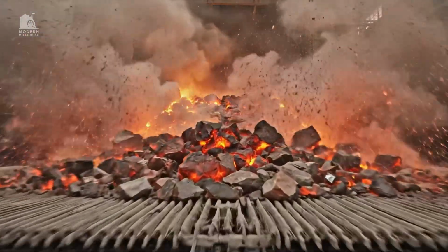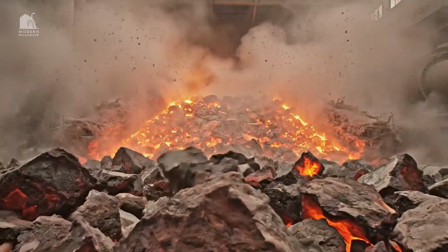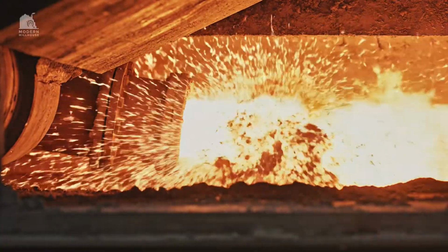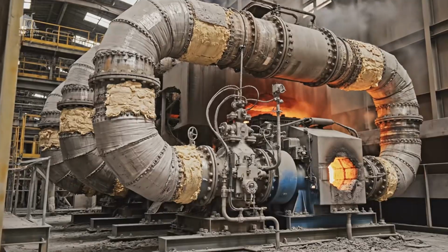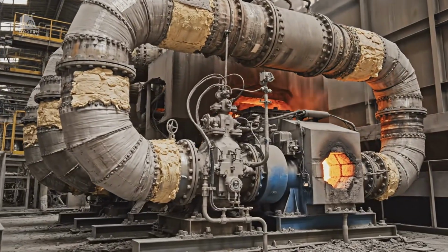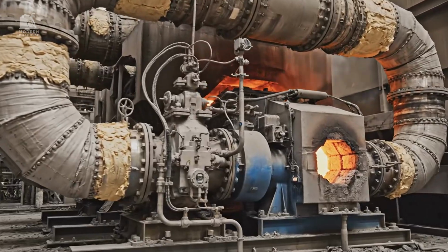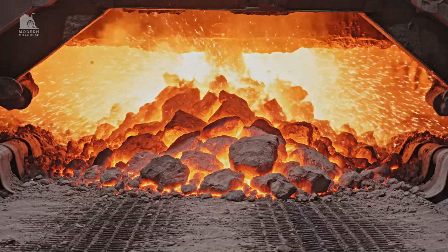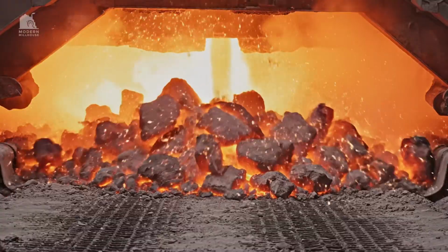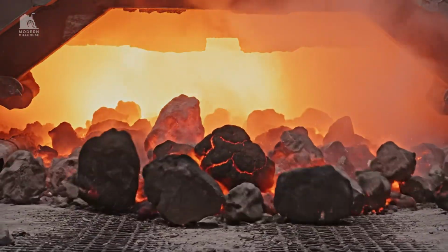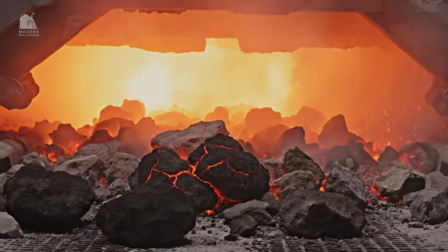The cooler turns clinker heat into usable combustion air. Secondary air from the cooler supplies most oxygen for the flame, and its temperature strongly affects fuel demand. Clinker leaves the kiln extremely hot, so the cooler must pull heat out fast without creating excessive dust.